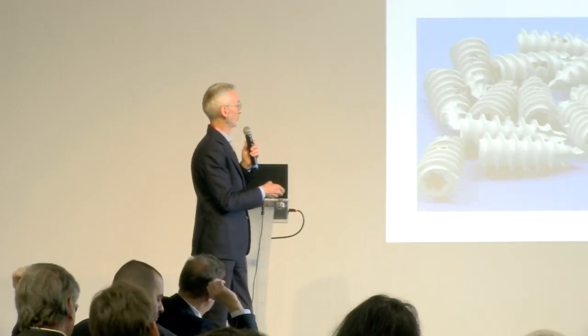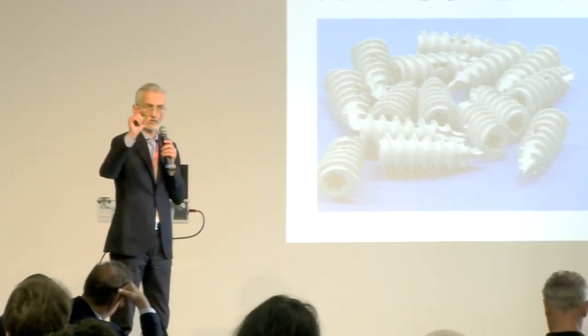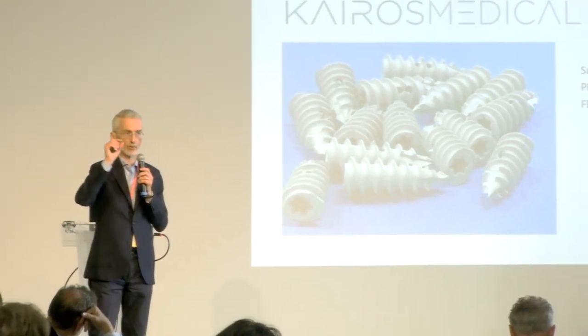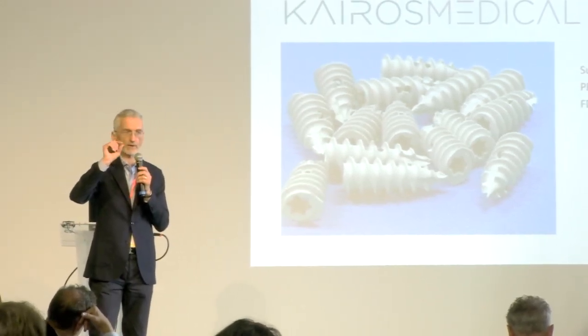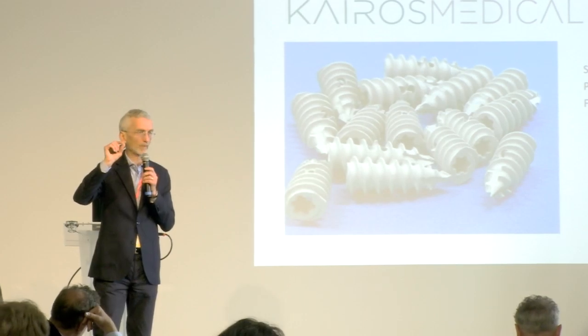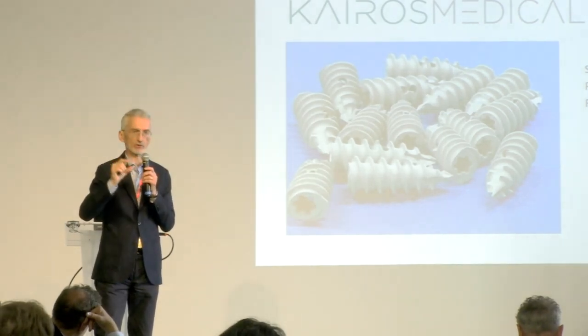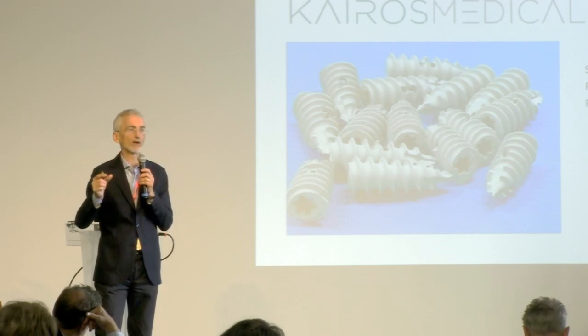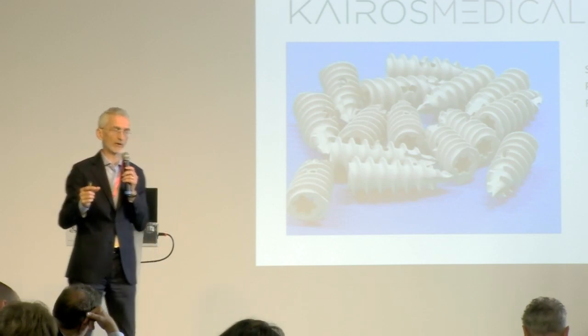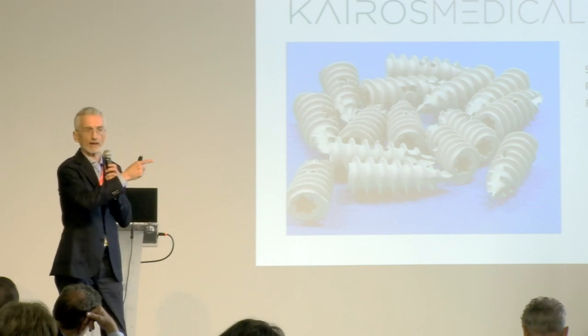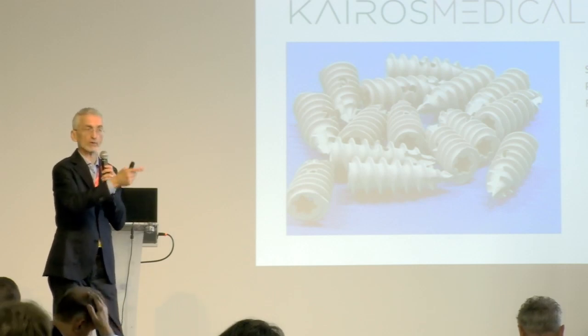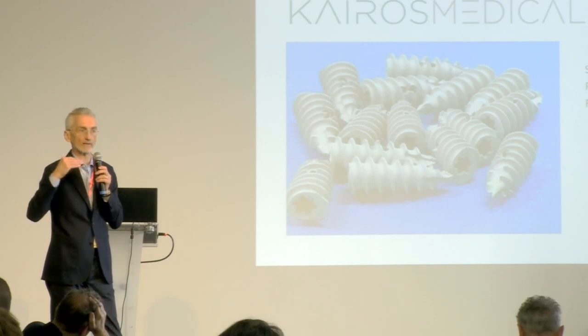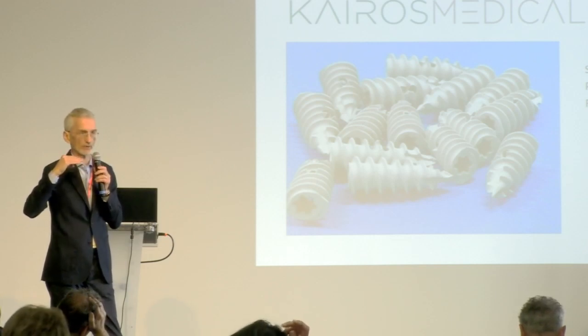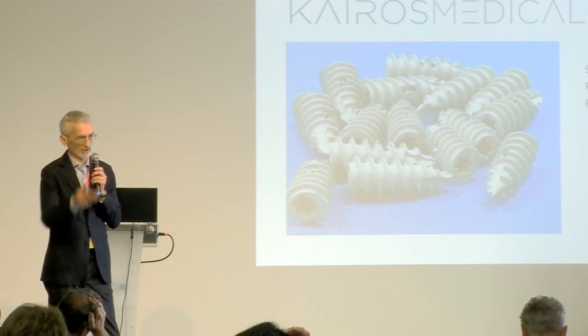That's a very good question. For example, if you take these suture anchors, you can contact them at the outside of the threads. So there will be, let's say, a very small area on the outside of a thread which is not coated, but it's not really an issue. You try to contact the implants where it's not critical. Especially if you've seen the comparison between coated and non-coated with these alloys, they are already very slowly degrading. These new generations are really good. So, very good question. Thank you.